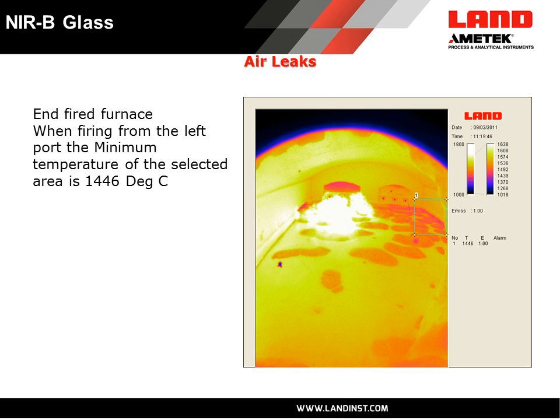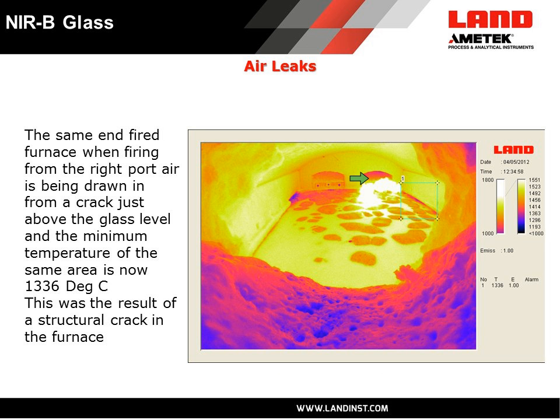Now we have the very same glass tank being viewed when it is being fed from the right side burner port now to the left side, which is now the exhaust port. The same area of interest is being shown, and it's calculating on the minimum temperature. And first of all, you might see in the image that it does look slightly darker down here, but also the temperature has gone down by almost 100 degrees Celsius, purely as a matter of from which side the tank is being fired.